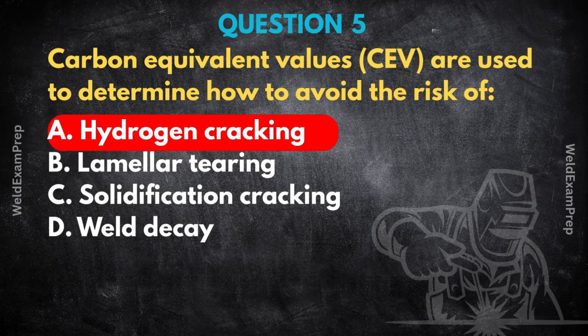And those hard structures plus hydrogen. Plus stress. You always need stress too. That's the classic recipe for hydrogen cracking. Remember, it's also called cold cracking or delayed cracking because it can happen hours or even days after the weld looks fine. Right, the delayed aspect is scary. It is. So the CEV calculation becomes a predictive tool. It directly guides crucial decisions on how to weld that specific steel safely. Primarily, it helps determine the necessary preheating temperature and sometimes the maximum interpass temperature.